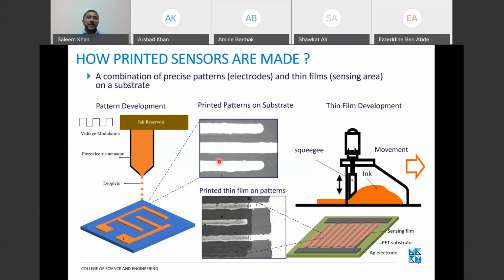So these substrates have specific requirements, like the surface properties, which are also dependent on the rheological properties of the solution. All these interactions result in very uniform structures, and these are really important so that we can achieve a very specific and precise distance, because in some cases we are using wide bandgap metal oxide materials which have a wide band gap. So in order to have a quick response, we need to reduce these sizes. So the substrate treatments and the properties of the solution are really interdependent, and we can tune all these properties to achieve very uniform layers like these.